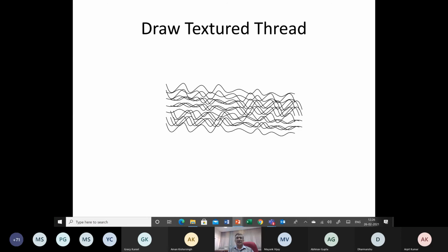bonds, they are relaxed. So when it is coming out, then we give the heat setting, which is very close to 180 degrees centigrade for the polyester, and it assumes a helical configuration. So that gives the bulkiness. Filaments are not straight, so they assume a helical configuration. So what I am showing is a single draw textured yarn. Then you take 2-3 such yarns and twist them, you will get the draw textured thread.